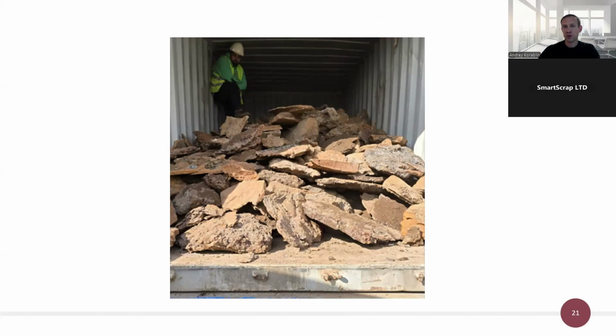We reached out to the producer. The response was that this scrap was metal that had been loaded into the furnace but had not yet melted. But that's not actually the case. Liquid metal from the electric arc furnace flows into the ladle furnace. Unmelted scrap cannot reach the ladle furnace. In the ladle furnace, slag is formed using lime to conduct specific processes. During slag tapping, some metal also flows out and solidifies on the slag dump. It is then recovered during slag processing. And we had to write the process description ourselves and successfully resolved the customs clearance issues.